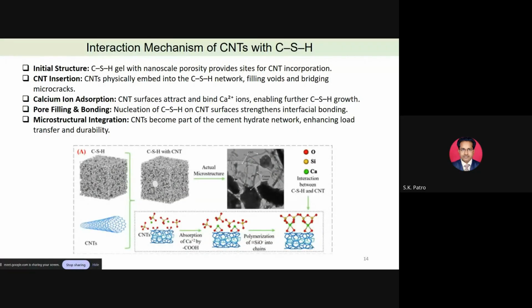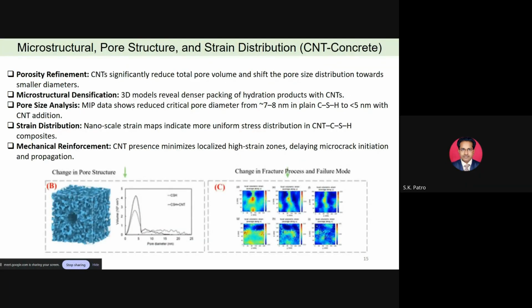This process shows how the carbon nanotubes assist growth inside the porosity, and how they enhance reactivity and hydration; all those things are discussed. CNT significantly reduces total pore volume, and shifts the pore size distribution towards smaller diameters. When the concrete is improved by its pore networking, then automatically you will see that it is refining the porosity. Microstructural densification: 3D models reveal denser packing of hydration products with the CNTs. If you look at the three-dimensional model, you can see pictorially how densified the substance is.